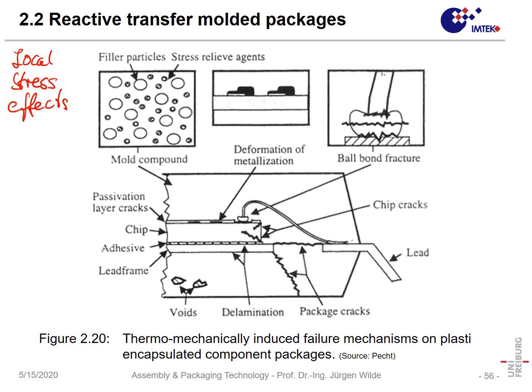For instance, often in such devices we have sharp edges or corners. And as an important engineering rule, we can say always at sharp corners inside materials or at edges, we have stress concentrations. We have stress concentrations here on the silicon. We have stress concentrations here on the lead frame. And of course, what would be very good is when we have rounded edges. But how to make rounded edges in silicon? That's not so easy, and it's very expensive, so it is often avoided.